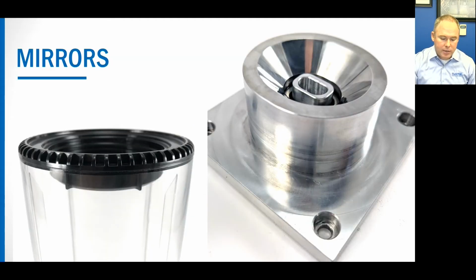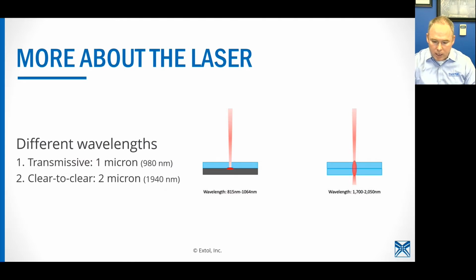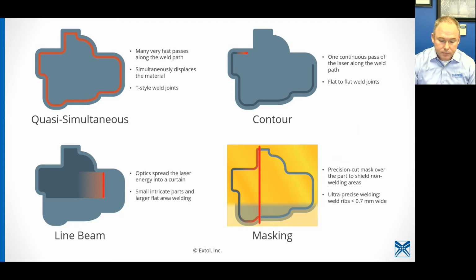So we talked a little bit about the lasers. I want to get into the multi-passes. There's a couple different types of laser welding out there. Quasi-simultaneous is probably the most common that we see. We're essentially moving many passes along the weld rib with one beam. And you can use a variety of different weld joints. We say T-joints here, Jason, but that's not exactly true. And we're simultaneously bringing the temperature of the melt rib up to temp. So that's why quasi-simultaneous, if we can do it, is usually the best.